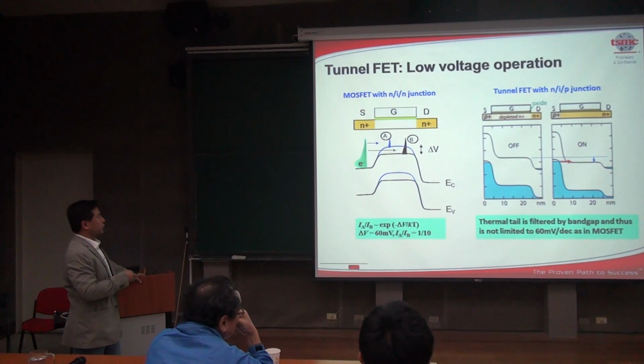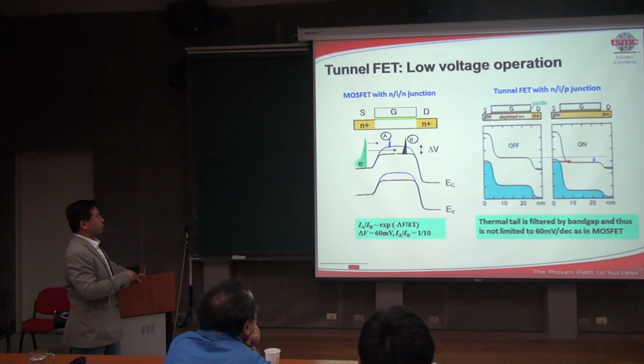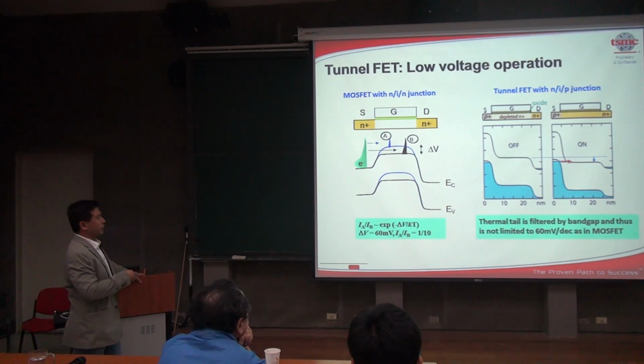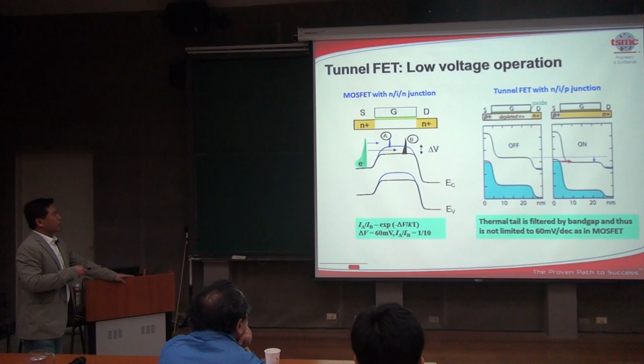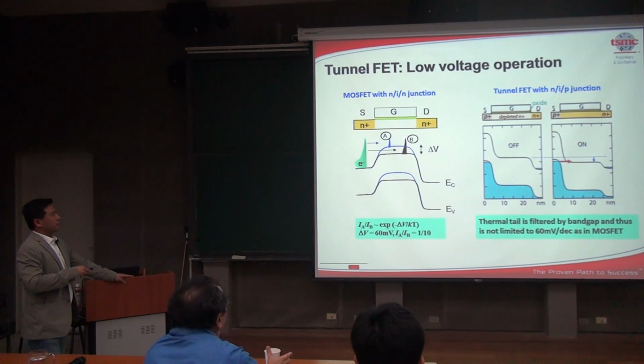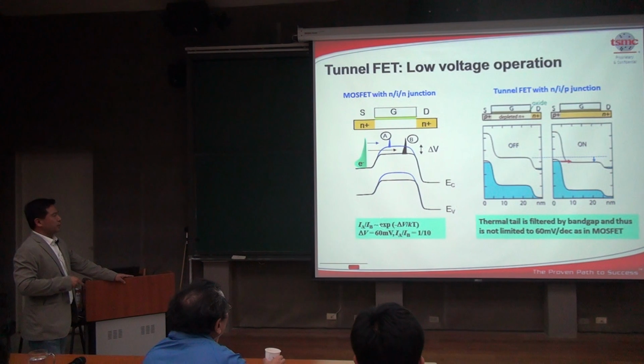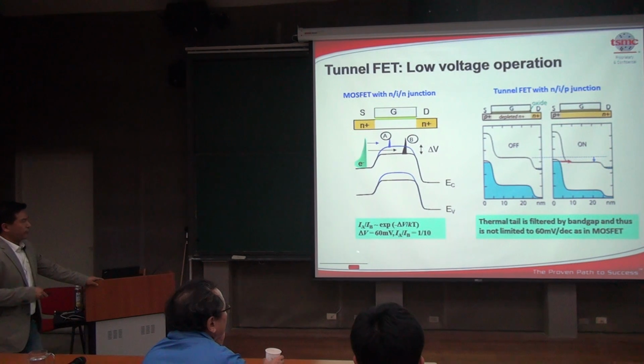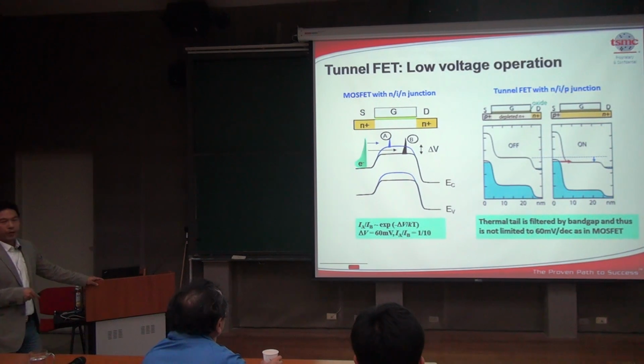In the off state, you use the gate to change the electrical potential in this barrier area. So suppose you have two potential positions, A and B. This is a Fermi-Dirac distribution of your carriers. The carriers that can go through the barrier are in this thermal tail that has the Boltzmann distribution. So the ratio of the A and B current is equivalent to this very simple equation that dictates switching behavior, which tells you that when you change your voltage by 60 millivolts, you can only change your current by 10 times and not larger because of this thermal tail.